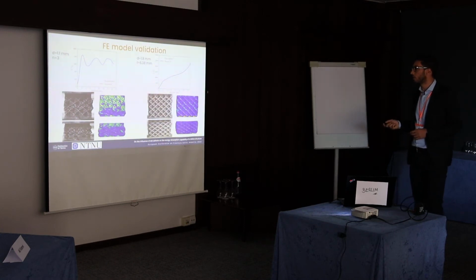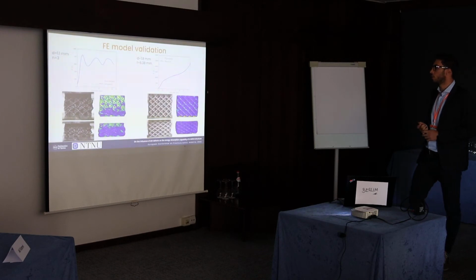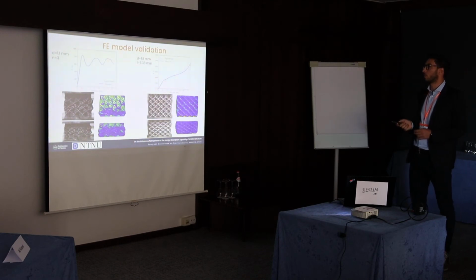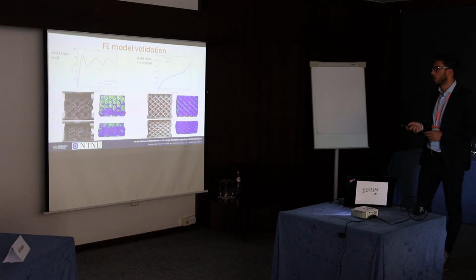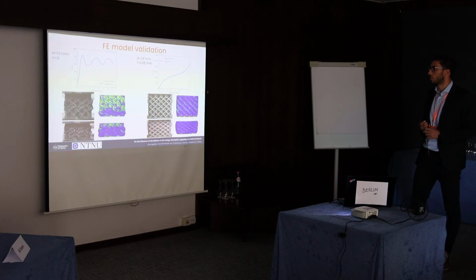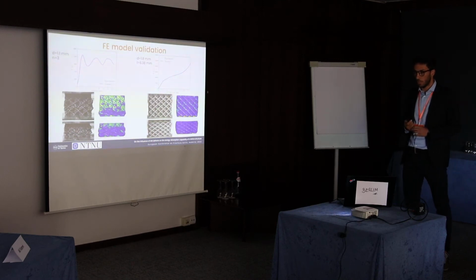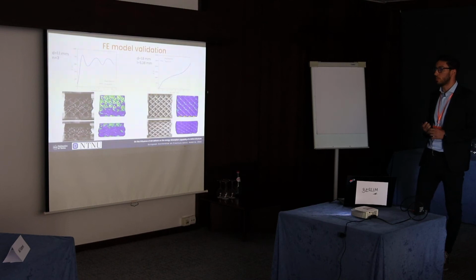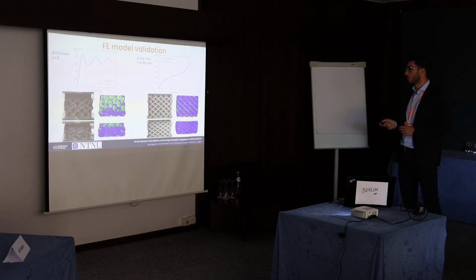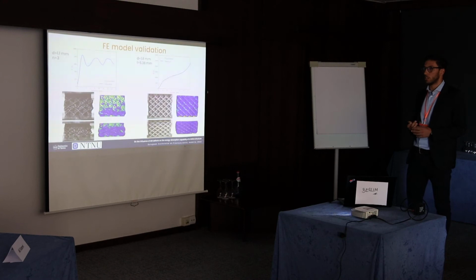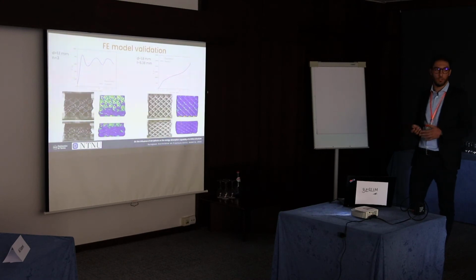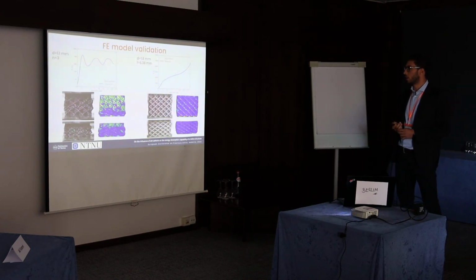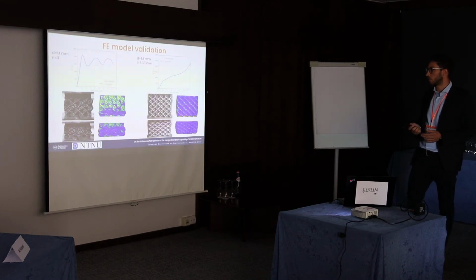While here on the right, you have a comparison for a lattice structure of the first factorial plan with a diameter of 1.8 millimeter and a length of 6.38. That was actually the most dense structure that we investigated. And you can see that in this case the crashing behavior is completely different. It is a foam-like crashing behavior. And even in this case, the numerical model is able to capture well the failure and the crashing behavior of the structure.